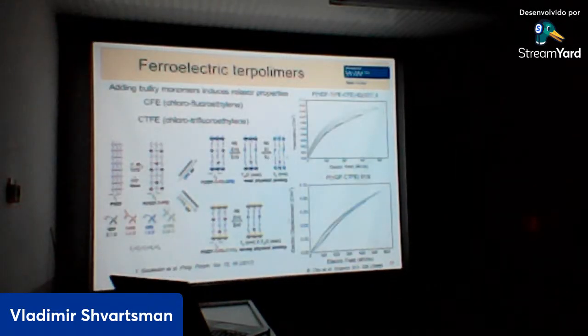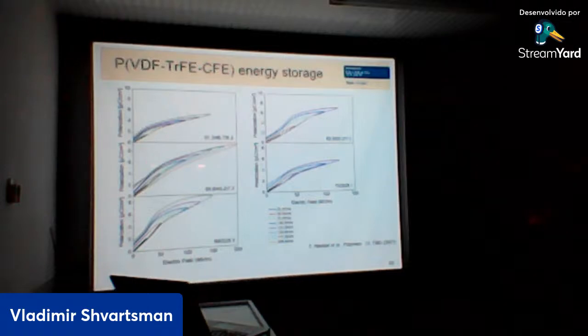Therefore, we have to destroy this ferroelectric state, and one of the strategies is to introduce another monomer, for example, chlorofluoroethylene or chlorotrifluoroethylene. So then we have kind of terpolymers like this one or like that one, and these terpolymers show typical relaxor behavior. They show slim hysteresis loop, they show a broad peak of the dielectric permittivity and strong frequency dispersion of the dielectric permittivity. So this is one example of these terpolymers with different content of the third monomer of chlorofluoroethylene. You see, when we increase the electric field, our polarization is going up.